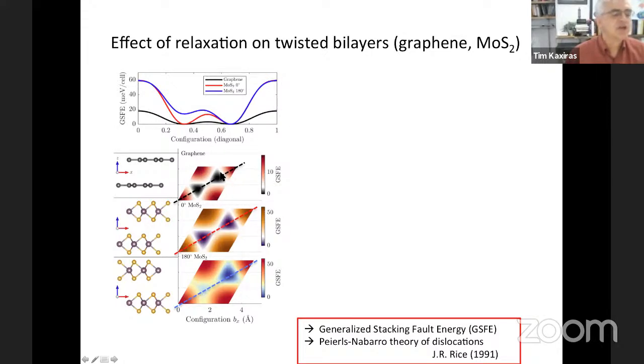So as a function of configuration, this is what the energy looks like. For graphene, this is the black line. So imagine sliding the two layers of graphene on top of each other. And this is the energy landscape that you can generate by this. If you take a diagonal cut through this energy landscape, this is the black line. The other two pictures correspond to molybdenum disulfide at 0 degrees and molybdenum disulfide at 180 degrees, the red and blue lines. Let's not worry about this for the moment. This is just to indicate that we have looked at many other systems, not just graphene, and especially the transition metal dichalcogenide systems.